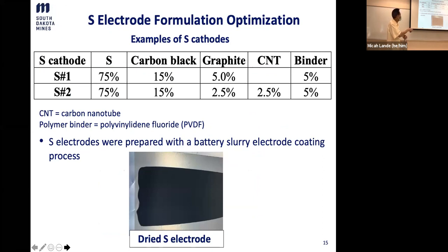Some people put even 50% of sulfur. The rest is all conductive medium. So the drawback is that you have so much dead weight, and then you don't really realize your advantage, because once you put so much dead weight, your battery is almost equivalent to the lithium ion. So when you balance this off, you want to minimize all the inactives. You want to maximize the sulfur active material, and that's the design guideline. Thank you.